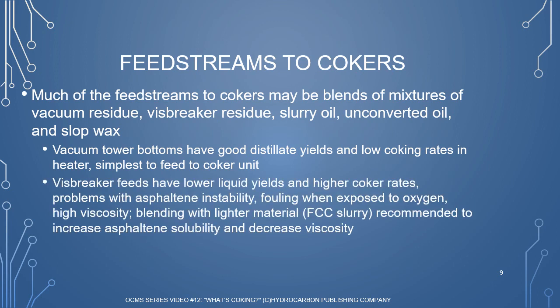Vis breaker bottoms will have lower liquid yield and higher coking rates, may exhibit asphaltene instability problems, high fouling rates when exposed to oxygen, and have high viscosities unless blended with lighter material, such as FCC slurry oil. Blending a lighter material like FCC slurry with vis breaker bottoms can increase asphaltene solubility depending on aromatics content.